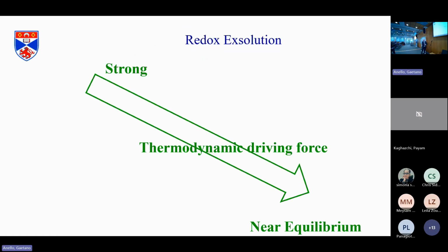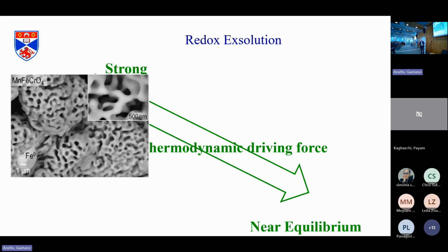Redox exsolution, we use reduction to drive that. And we would say that thermodynamic driving force is really important. If there's a strong driving force, you don't get subtle structures. If it's close to equilibrium, you can get some very stable, very subtle structures. So here you have grains of manganese, iron, chromium spinel. This has been strongly reduced and exudes metal particles.